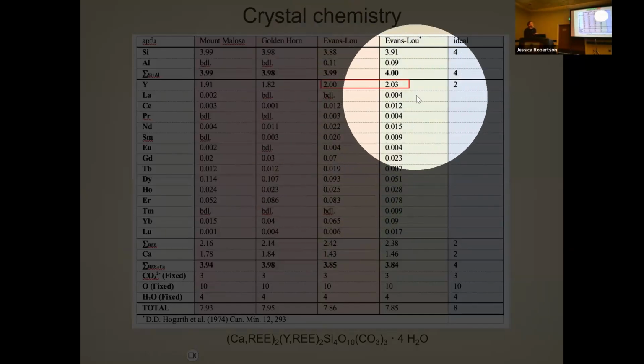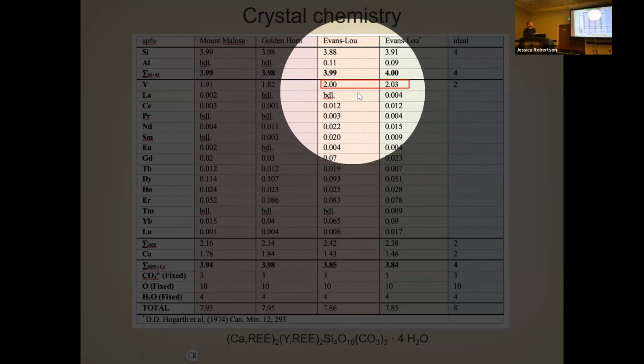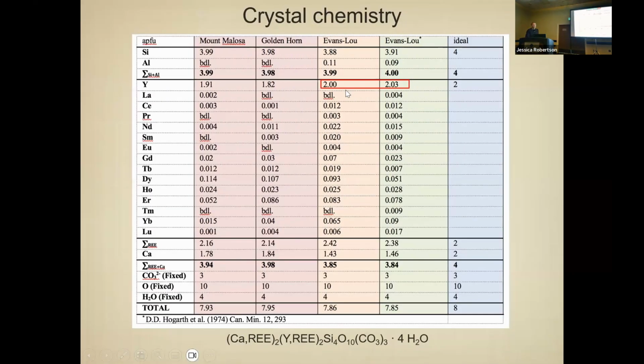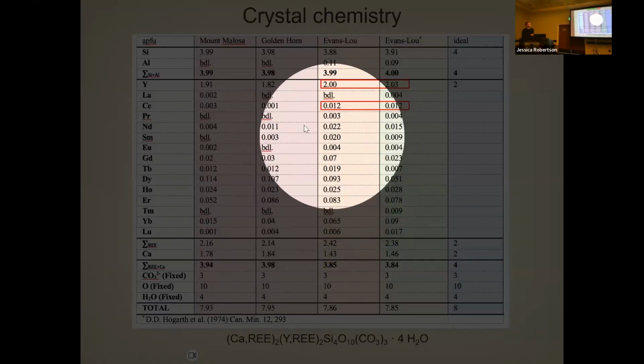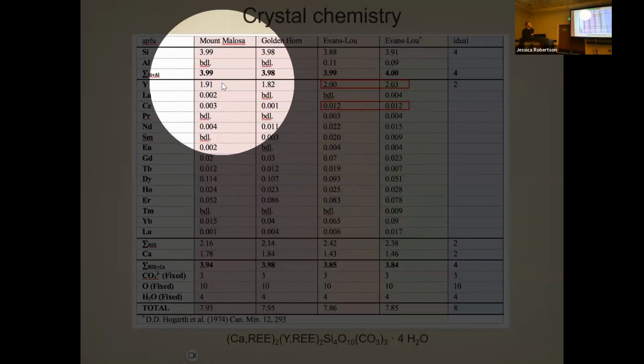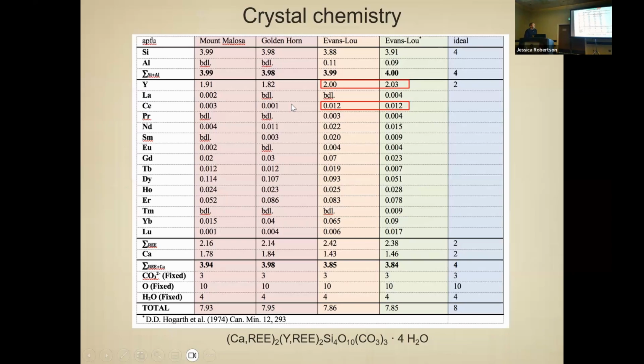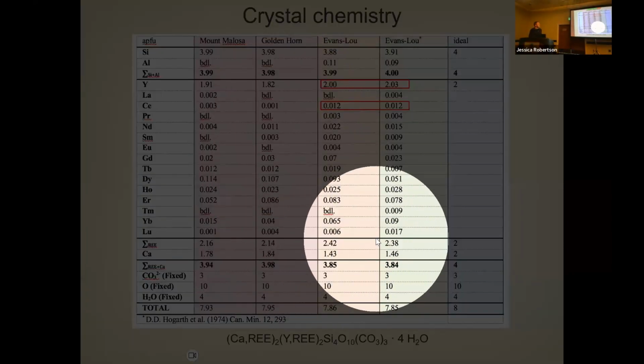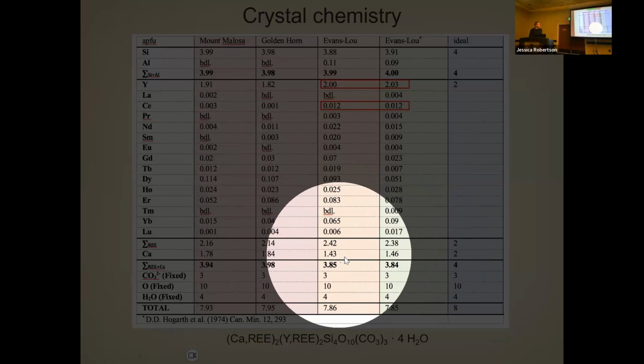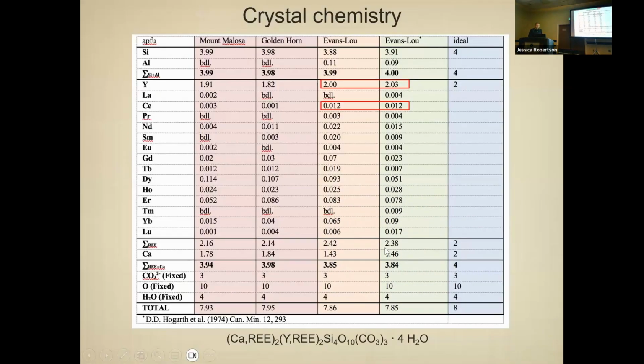And what we see, though, is that the confusing thing about the type material is that the yttrium site would already be completely full with yttrium. Now, if you add the other rare earth elements, all of which are higher than in the Golden Horn and Mount Malosa, where we have a lower yttrium content, you actually have an excess of the rare earths for the yttrium site. And you have a deficiency at the calcium site.